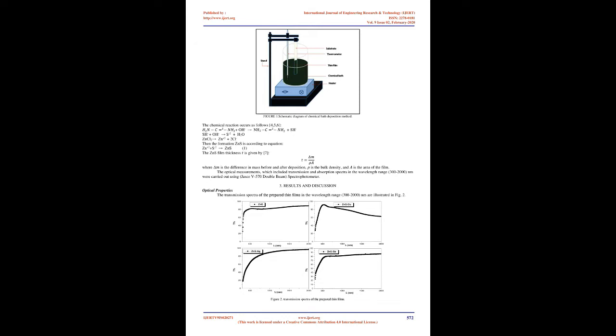ZnS films were deposited chemically using 1M zinc chloride, ZnCl2, as zinc ion source, 1M thiourea, SC(NH2)2, as a sulfide ion source and ammonium hydroxide, NH4OH, to control pH value. The total volume of the chemical bath was 100 ml. These solutions were mixed together in a separate beaker. Afterwards the mixed solution was stirred for 15 minutes. The pH value was maintained at 11.6.